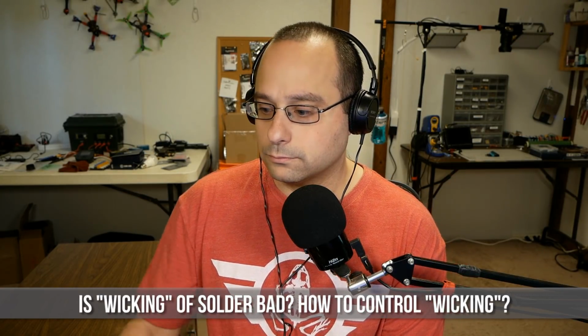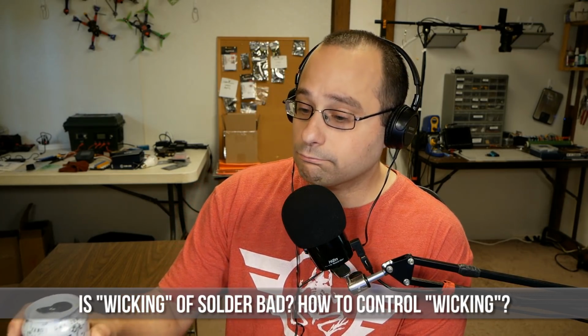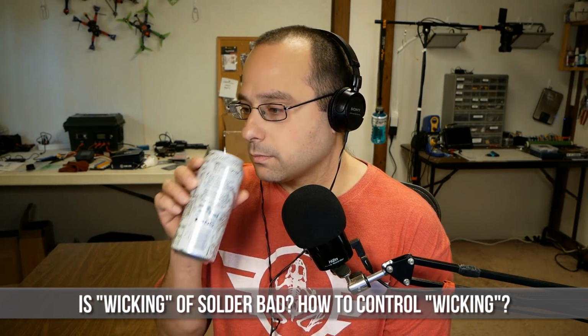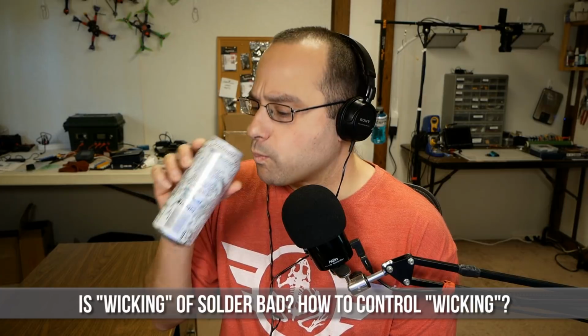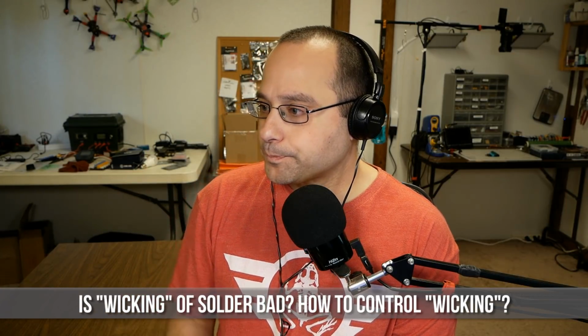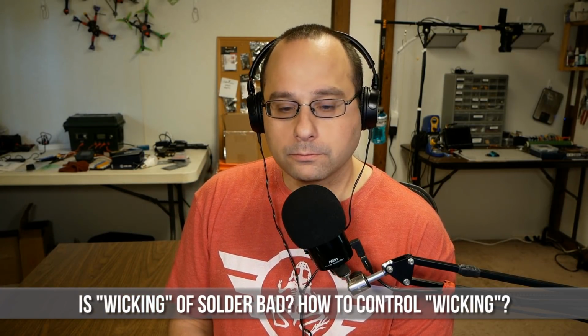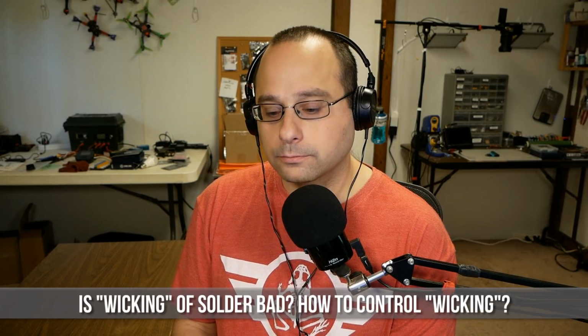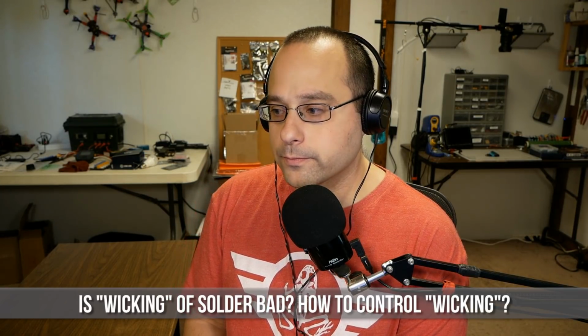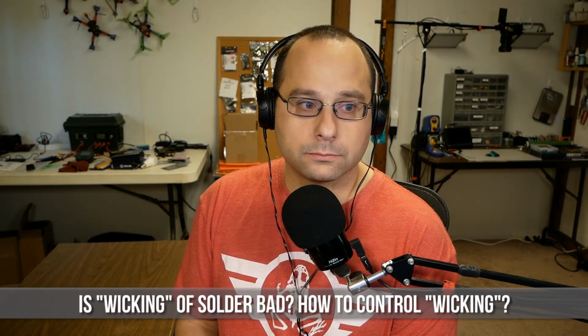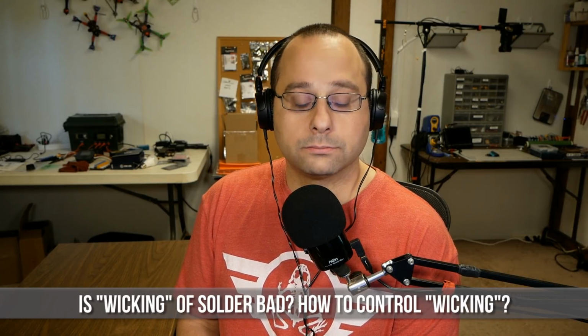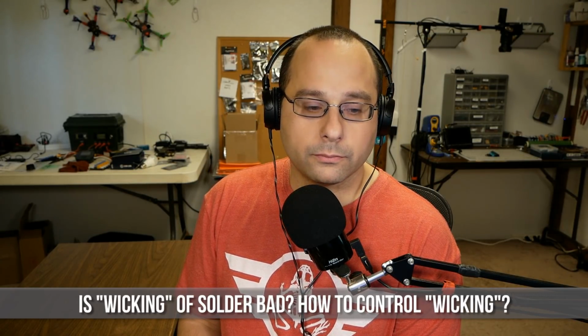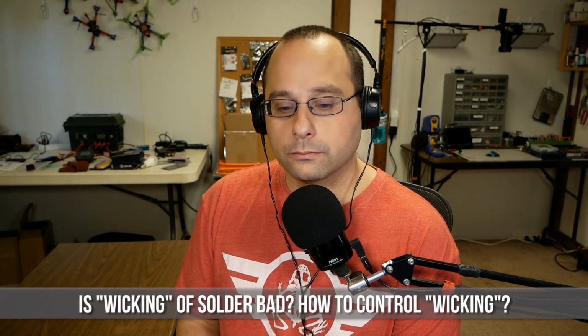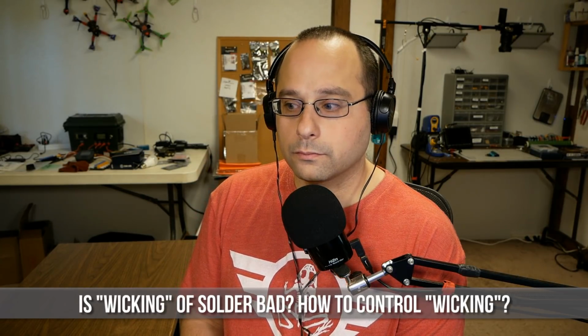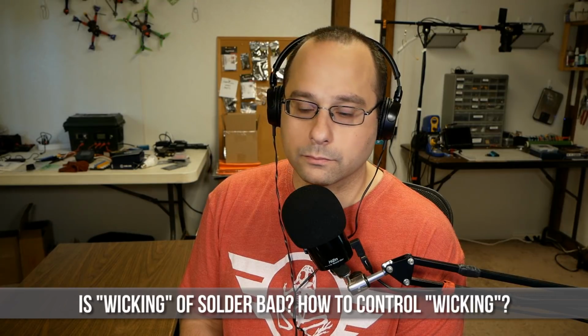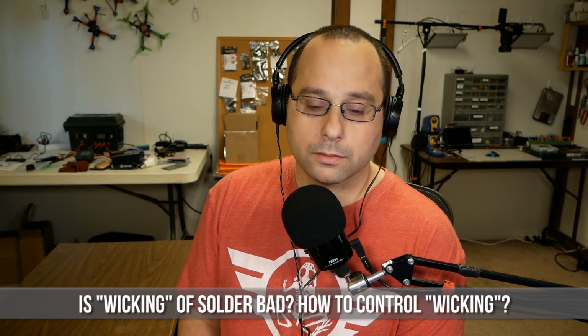It's actually not bad unless it's a problem in your application. You're trying to bend that wire to get it into a certain shape. As long as you've got a good solid joint, let's say you twisted the wires together, you're not doing like a butt joint. It's okay if the solder flows into the strands of the wire, because that makes the bond stronger. The only problem is if you're trying to bend that into a small shape, or it becomes difficult for you to maneuver that wire where you want it to be inside the board of the copter, then it can be a problem for that application.